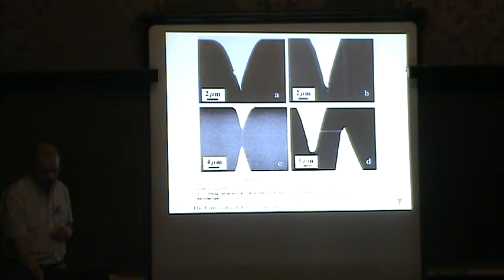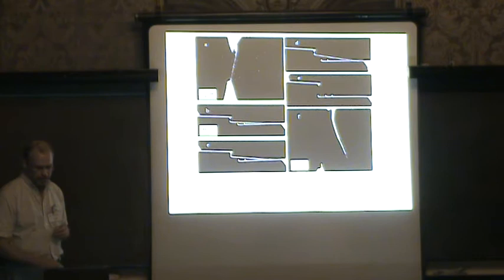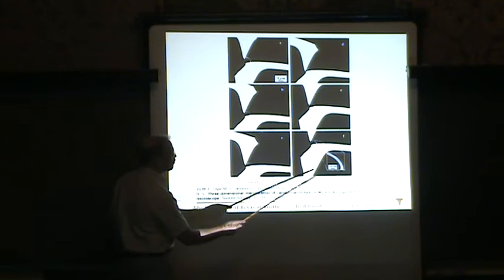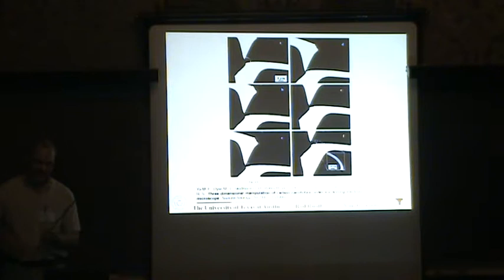So in this paper, we were sort of developing our techniques and mounting nanotubes across the opposing tips and moving the tips with respect to each other in space. And we could actually break some of the tubes. The images that we were taking at home are much clearer in terms of the images. We could cause buckling in the tubes. If you look very closely here, this is actually a tube that has a large number of kink flows in it. And that's a consequence of compressing to drive the buckle formation.